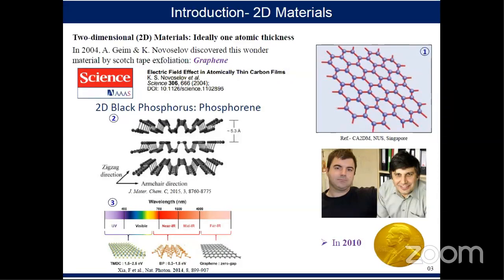Then black phosphorus came, whose 2D form, phosphorene, has a direct band gap irrespective of its layer number. It has anisotropic directions, zigzag and armchair. It has a band gap of 0.3 electron volt in bulk and 1.5 electron volt in monolayer form. So it exactly bridges the gap between TMDs and graphene. My talk is based on these phosphorene nanocrystals, which we have synthesized in our lab and applied. Next slide.